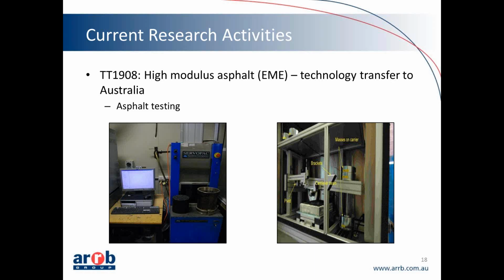Some of the testing that we did for this project was gyratory compaction using the servo pack at various different cycles to determine workability. We did that at 150 millimetre diameter, which you can see there on the left-hand side. Then we did an evaluation of its rutting, which is basically just deformation, similar to what I've discussed previously, but at a much lower scale. We're looking at around between 15 and 20 kilos worth of material.